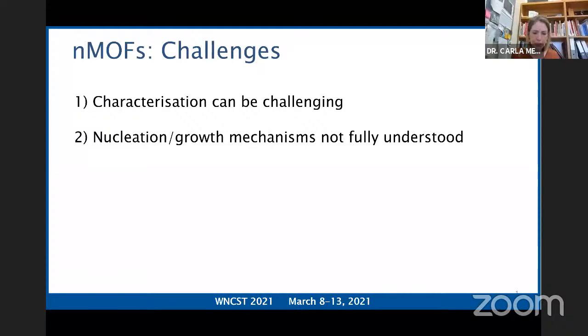There are some proposed theories that hold true in many cases, and in fact sometimes in most cases, but there really doesn't seem to be any theory that applies all of the time. So to address these two challenges, with respect to the first challenge and the characterization, we've really been inspired by some of the key developments in electron diffraction techniques that allow the collection of three-dimensional electron diffraction data for crystals in the size range of about 10 to 100 nanometers using transmission electron microscopes. So this has enabled structure determination of both micro and nanocrystals.